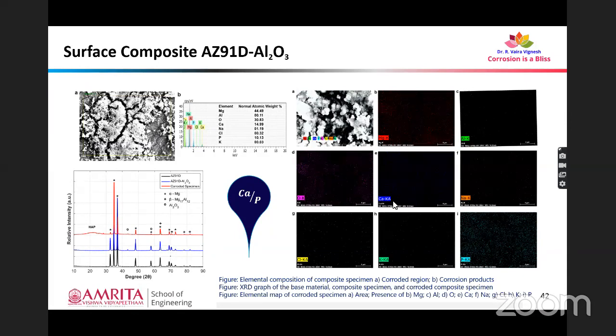So the major parameter we have to analyze when we subject a material to simulated body fluid is the calcium to phosphorus ratio. Why? Because the calcium to phosphorus ratio will give us an idea about the formation of hydroxyapatite crystals in the corrosion product. If there is a formation of calcium hydroxyapatite crystals, that confirms that the material will have good biocompatibility. Why? Because hydroxyapatite is a very good biocompatible compound. Why? Because this is the inherent material that is present in the bone itself.